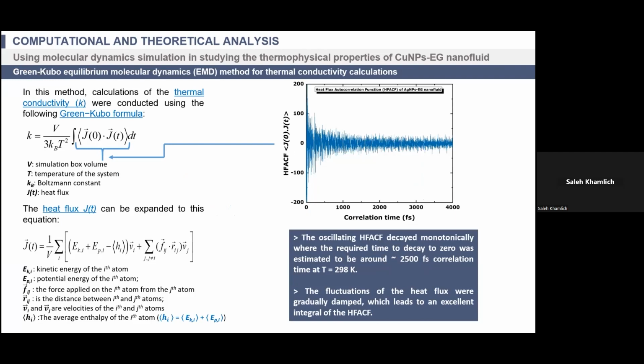So after doing all of that, we now have to extract the thermal conductivity. We applied what we call Green-Kubo equilibrium molecular dynamics. This equation was applied within the algorithm in order to extract the thermal conductivity from the system. As I mentioned, this is a heat flux autocorrelation function. Of course, the molecules are vibrating and they will be stable after some time. They will reach what we call stability. So after it approaches 0, we do our integration and we extract what we call the thermal conductivity.